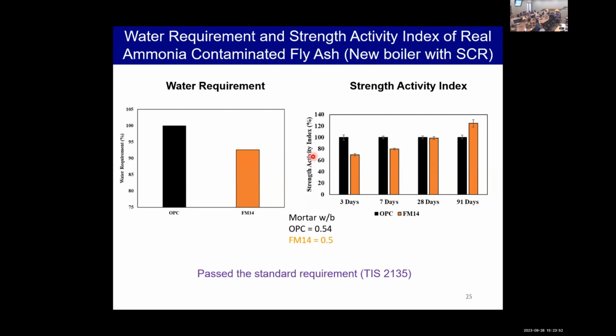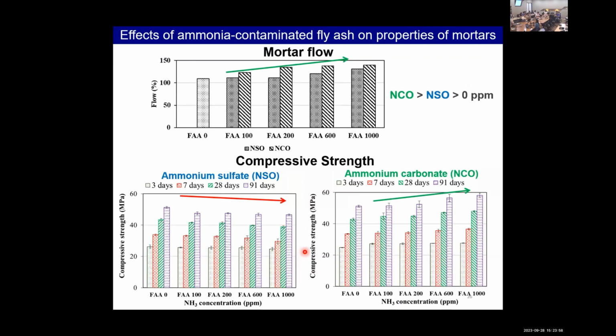We found that the fly ash from this type of boiler passed the standard requirement. And actually, for the sample, the contaminated amount may be very low. So in our study, we extended it by adding ammonium salts like ammonium sulfate and ammonium carbonate, which are the common types of salt that may contaminate fly ash, into our samples, varying the ammonia concentration up to 1,000 ppm. The results show that the mortar flow can be increased when the fly ash contains ammonium salt.